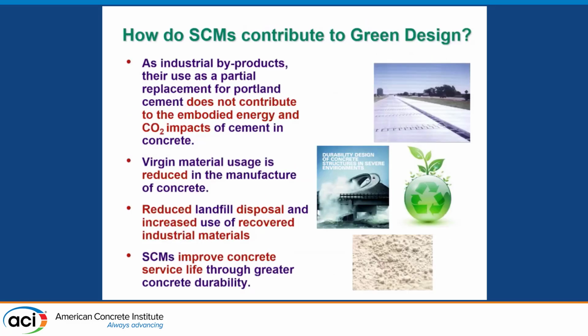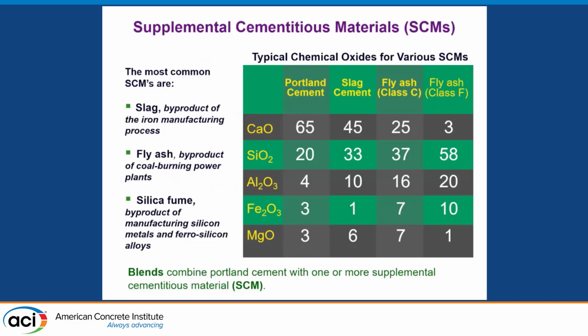So certainly industrial byproducts are big into this, and we've talked about silica fume, fly ash, and certainly slag. It reduces landfill disposal, obviously, but it does improve service life, as I've shown in the last section. And certainly here are the most common SCMs, but if you come today to ACI, you see things more like volcanic tuffs. You're looking at bottom ashes. You're looking at other new materials, ground granulated glass. Things like that are coming into the marketplace.